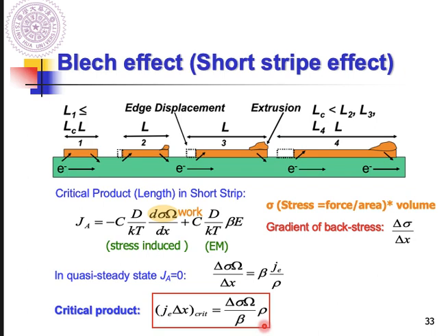So we got this relationship, right? As long as you determine what kind of material you are going to use for this interconnect, you definitely know the electrical conductivity, average atomic volume, and also the effective charge. You can measure this like in the previous slide, the one we just mentioned in EM, on how to determine the effective charge.